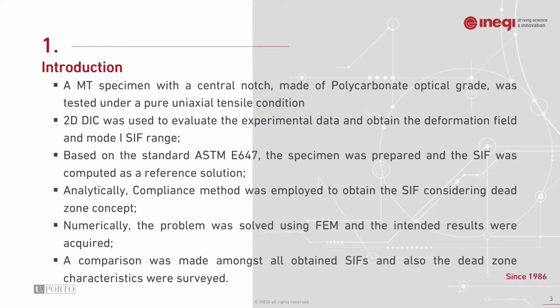Moreover, based on the ASTM standard, the specimen was prepared and the SIF was calculated as a reference solution, and the compliance method was employed in order to acquire another stress intensity factor based on the dead zone concept, that is the main goal of this work. And computationally, the problem was resolved using the finite element method, and the obtained results were acquired in order to make a comparison between all the obtained results, and also the dead zone characteristic has been surveyed.